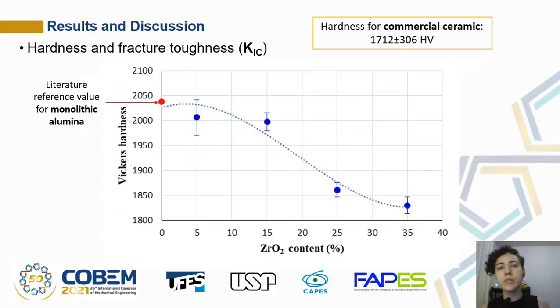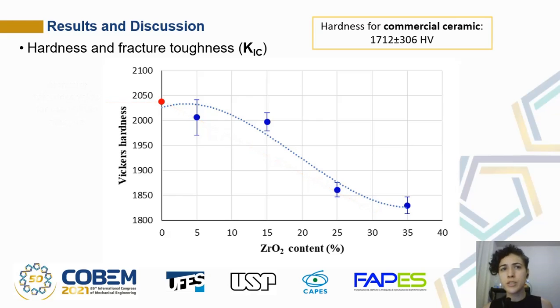With the increase of zirconia content, a decrease of hardness was observed. This fact can be related to the lower hardness of tetragonal zirconia in relation to alumina, and also the greater capacity to transform tetragonal zirconia into monoclinic phase, since hardness is inversely related to the ease of transformation. The porosity of the sample with 5% of zirconia is another possible factor for the drop in hardness compared to monolithic alumina. However, the Vickers hardness numbers evaluated for the samples were higher than those tested, including the commercial ceramic.